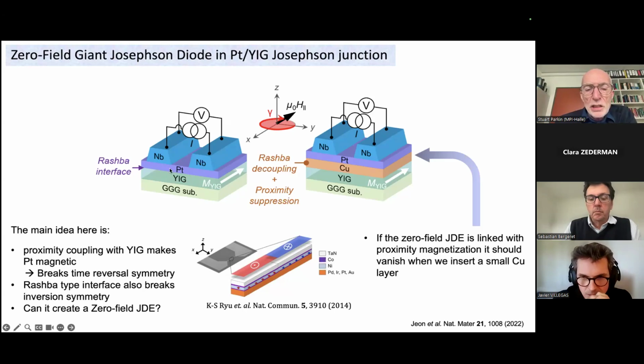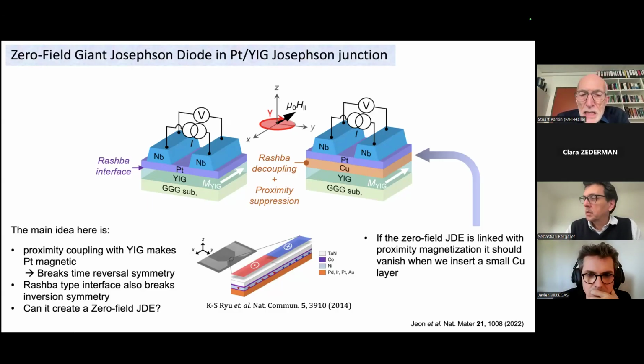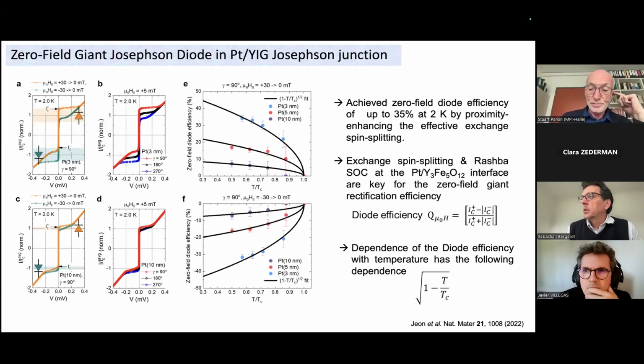Now we grow the platinum on top, and we have niobium electrodes separated by a relatively small distance. Again, the platinum can become superconducting by proximity to niobium, and it's magnetic by proximity to YIG, and now we see a diode effect. But we see this in zero magnetic field. And these are some results from this paper of ours from 2022.